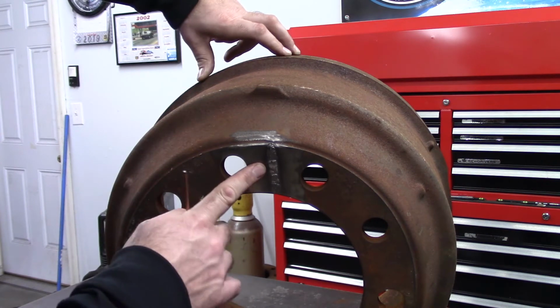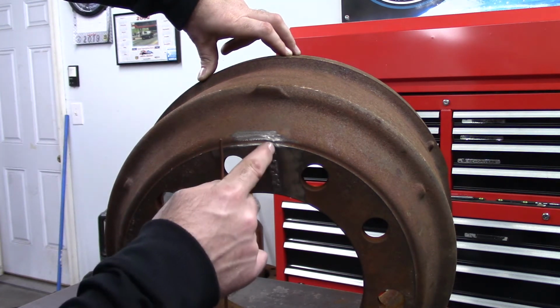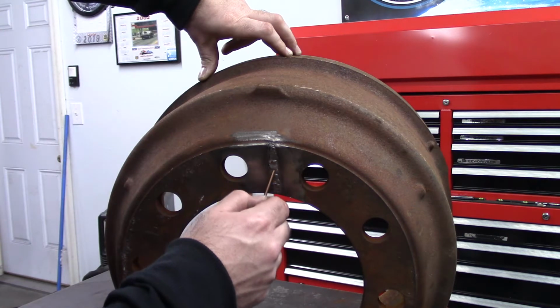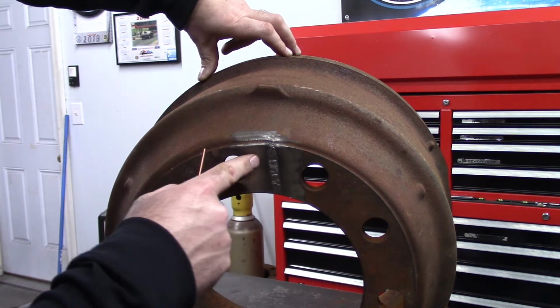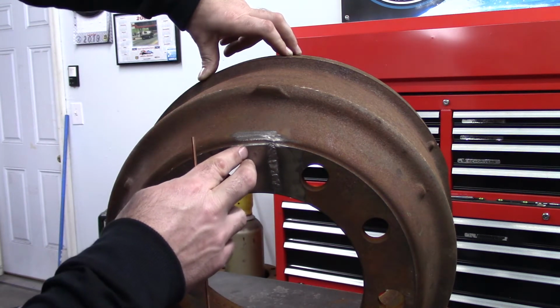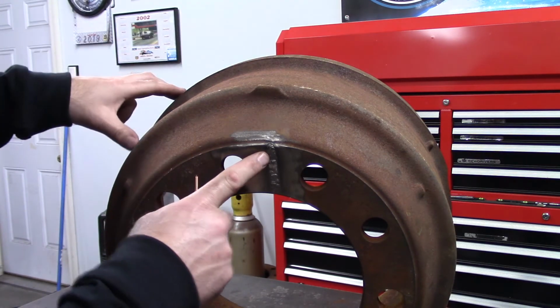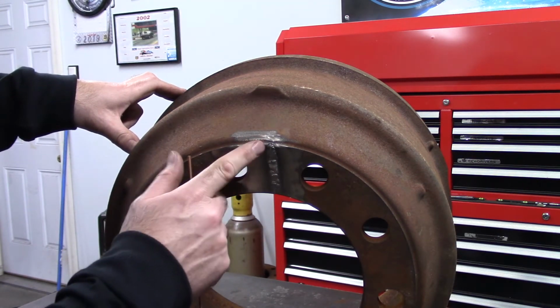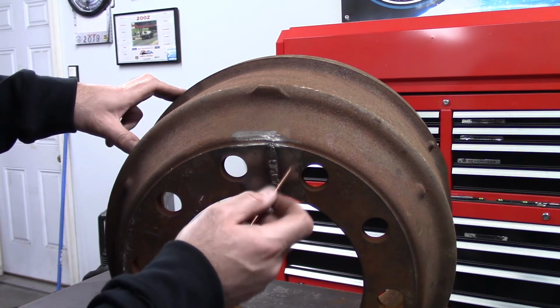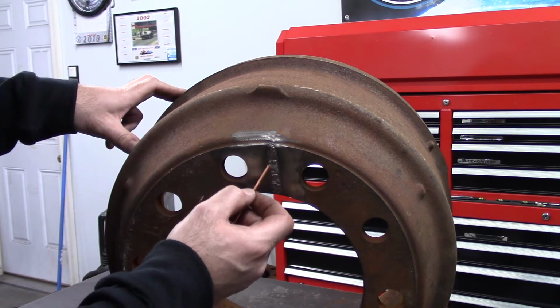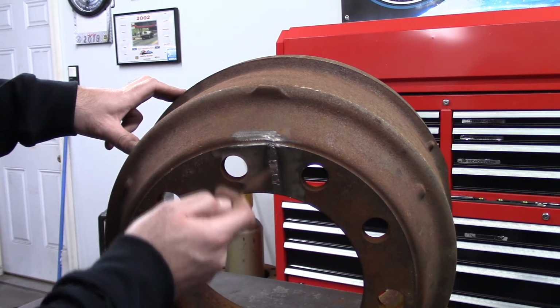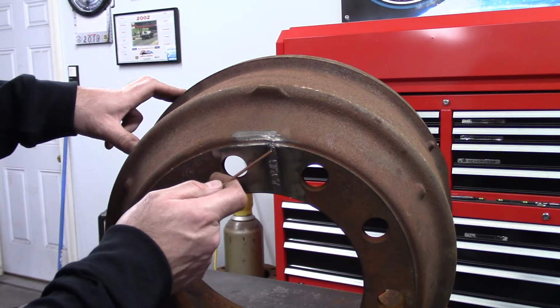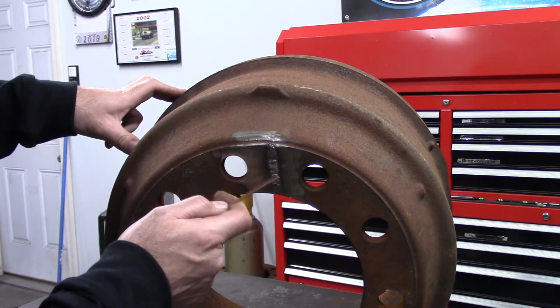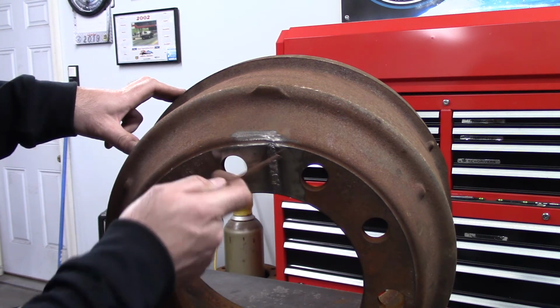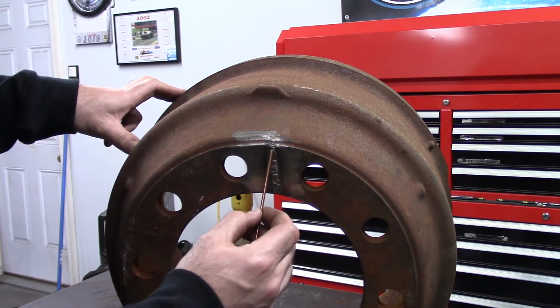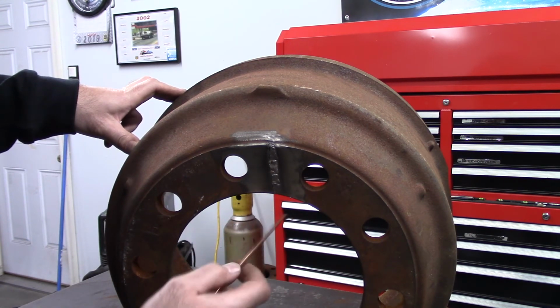With my test welds, I did notice some linear cracking that would go down the bead, but it was just due to overheating in my practicing. But this one here turned out really great. Welded a little bit, stop, let it cool, welded a little bit, stop, let it cool. And I actually jumped around a little bit, not to put all the heat into one spot and move the heat across. I put heat in all over the place. So I'm pretty happy with the way that turned out.